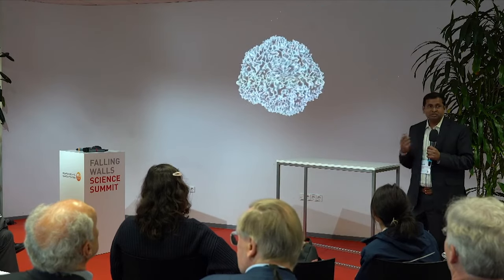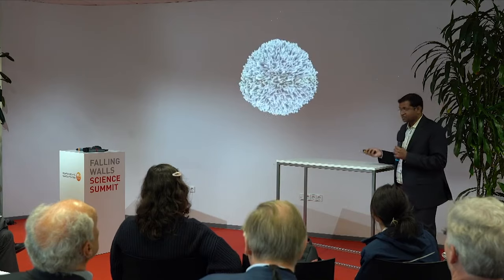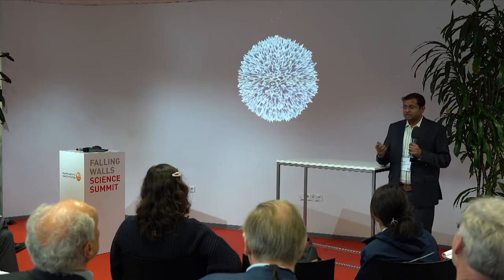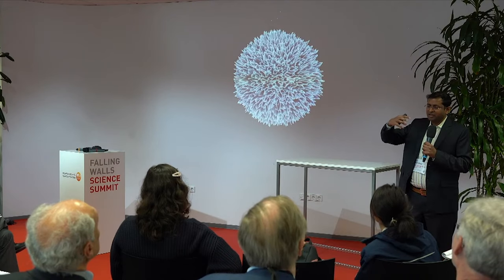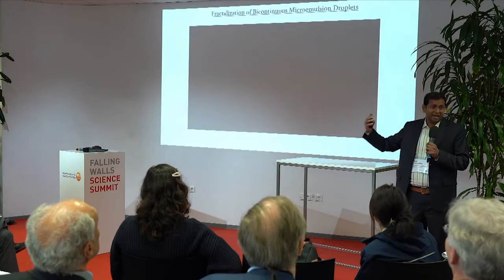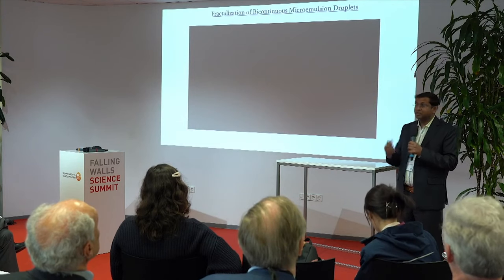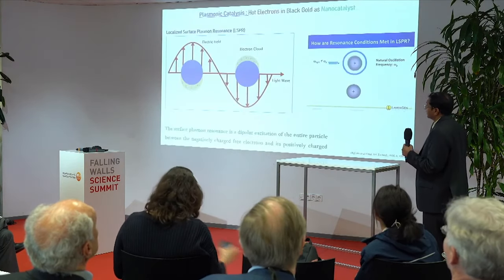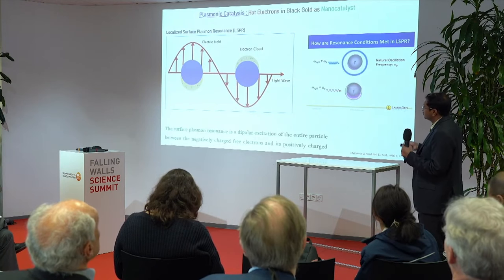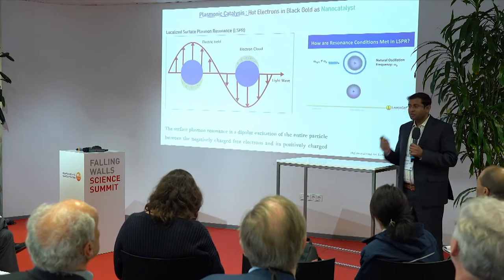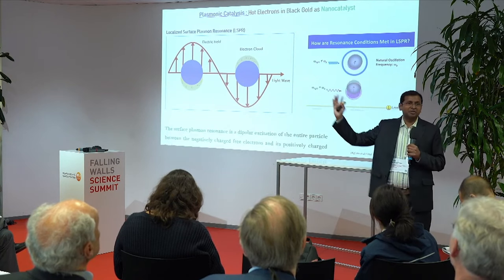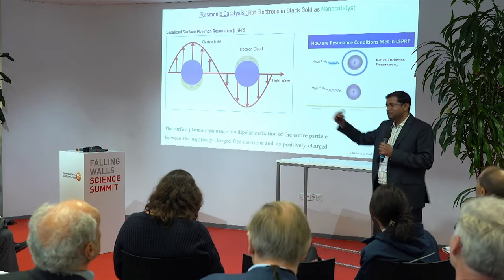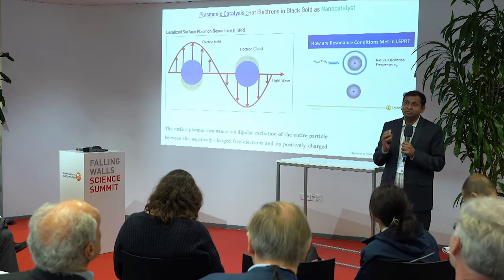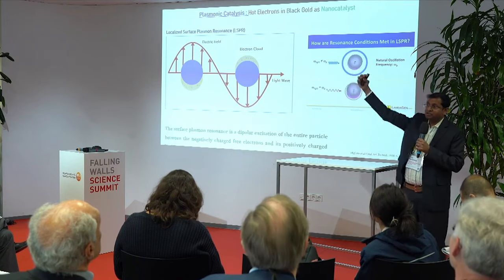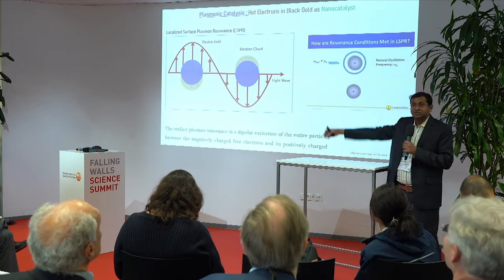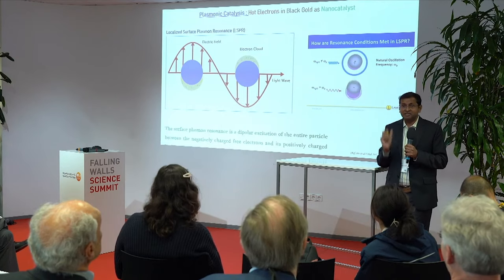So what we then try to do is use the concept of localized surface plasmon resonance, LSPR, which is more about the electron cloud on the metal nanoparticle resonating with some particular wavelength of the light, and that allows you to harvest those wavelengths of the light. It's a very simple way of explaining the LSPR, right? It's more like a resonance between the electron cloud and a particular wavelength of the light. However, if you make, say, 10 nanometer gold, it would harvest, say, 550 nanometer wavelength. If you increase the size, you will get a different wavelength. But if you really want to design a good photocatalytic system, then you should harvest all the solar photons coming from the sun, from, say, visible to near IR, which is not possible by simply changing the size of the nanoparticle.